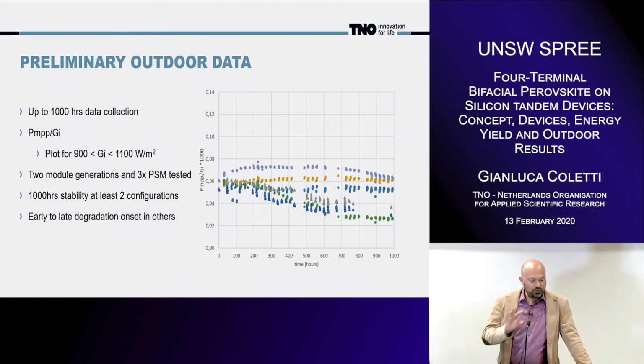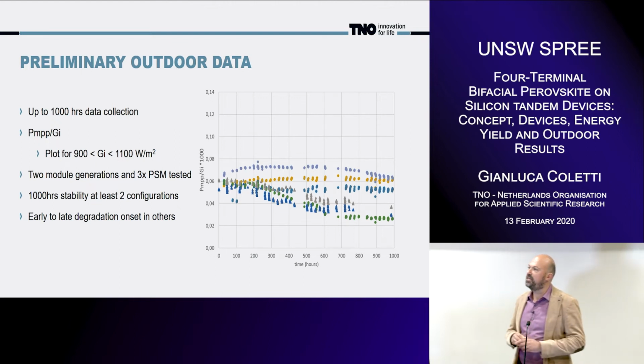So we tested two module generations. One is the one you saw before. We tested another one together with three types of perovskite made with different materials. And you see that for at least two of the configurations, so the match of perovskite and module generation, there is stability for the first 1,000 hours, while we already see an early onset of degradation in the other. So this already gives an indication of which direction we need to take to maintain the stability of the device, and especially how good a development you need to do when you integrate them into one module.